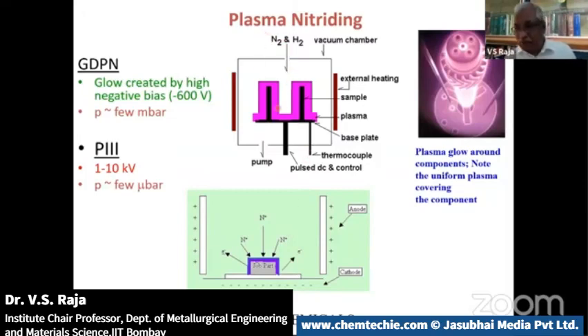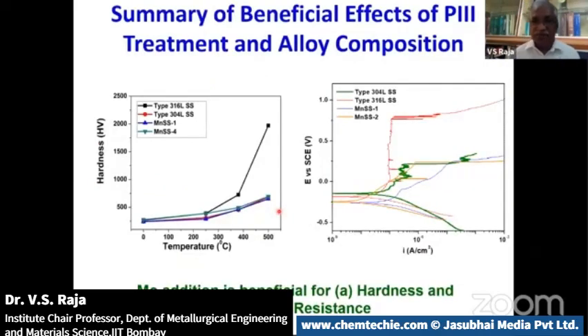This is plasma nitriding. One PhD student worked with us. Plasma ion immersion technique, another PhD student worked on it. This is for stainless steel. Stainless steels are excellent materials for corrosion resistance, right? But they are soft materials. Where, for example, you're going to use a valve in flow lines, you may not be happy with just corrosion resistance. You need to have higher hardness, higher erosion resistance. It's very important. How to do that? You use this technique. Again, we don't have much time.